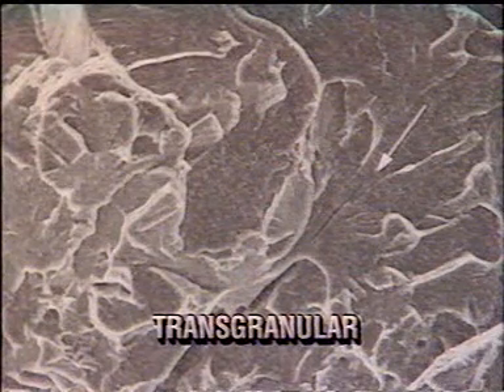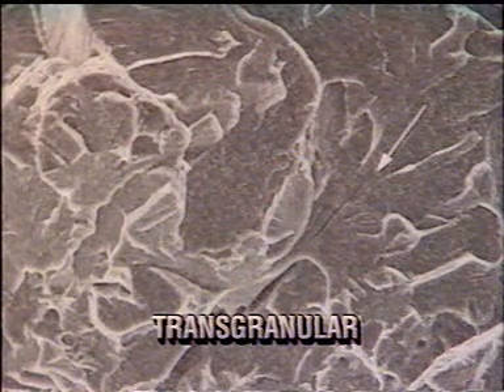Cleavage, the basic brittle fracture mode, is a low-energy fracture that propagates along well-defined crystallographic planes. These are known as cleavage planes. As mentioned earlier, cleavage is only one of 2 different brittle fracture mechanisms. The splitting cleavage along the crystallographic planes is transgranular. The cleavage occurs through the crystal grains.